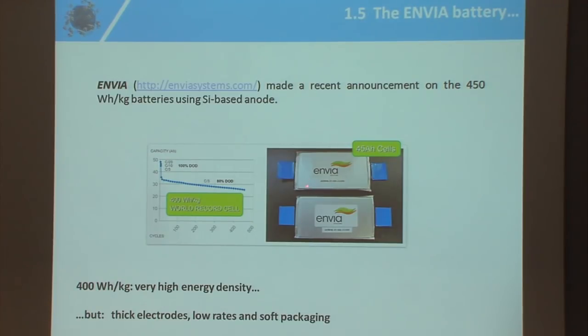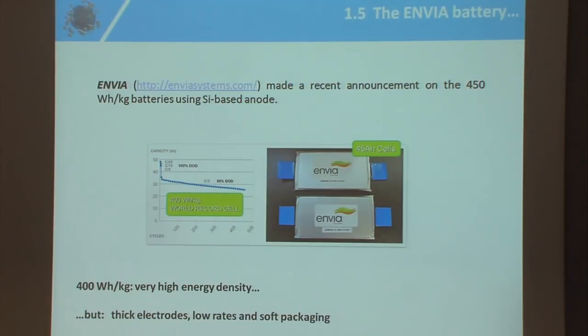And second, they use very thick electrodes, millimeter thick electrodes, so that you have in the same volume a lot of active material. But since you use thick electrodes, the power capability is very low. So this plot was certainly obtained at C/10, C/20, C/50 discharge, at very low rate. There is no power inside, so there is no miracle.